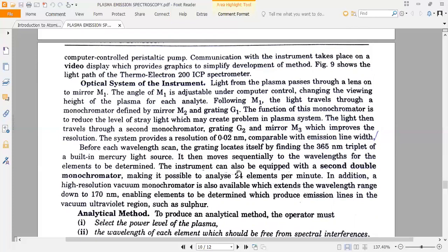The instrument can also be equipped with a second double monochromator, making it possible to analyze 24 elements per minute. In addition, a high-resolution vacuum monochromator is also available, which extends the wavelength range down to 170 nanometers, enabling elements to be determined which produce emission lines in the vacuum ultraviolet region, such as sulfur.